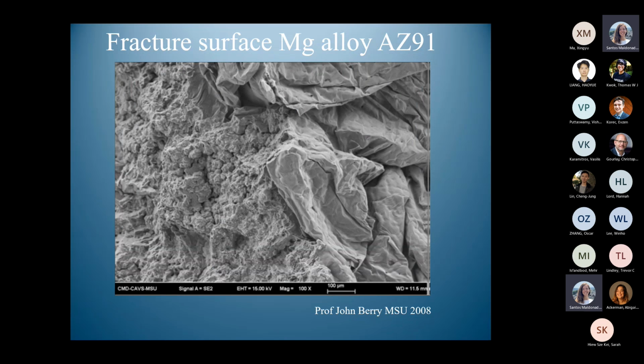And here again, this is the same magnesium alloy. And now the biofilm's in a much more crunched up situation. But although this is obviously a film, all of this as well is again biofilm. It's just that it's been crunched up incredibly small. But as I say, everything you're looking at is one of the biofilm films which has come off on that side of the fracture, and the other film from the biofilm will be on the other half of the fracture.